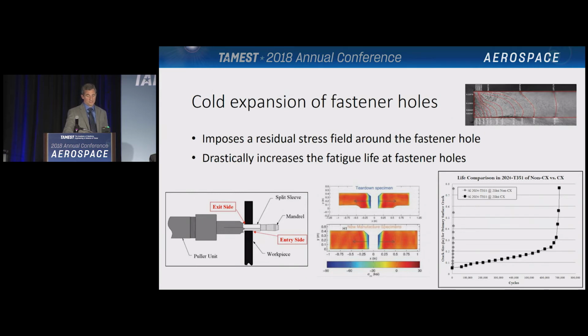So the picture on the bottom left shows how this is performed. A mandrel with a sleeve is put into a fastener hole, and then the mandrel is pulled back through the hole with the sleeve kept in place. Because the end of the mandrel, shown here, is bulbed, it pushes the sleeve into the material around the hole, stretching it to a larger diameter. This stretching causes the material at the hole to have a large compressive residual stress, which is shown in blue in this center plot here. The large compressive stress squeezes flaws in the material, making it more difficult for them to grow as fatigue cracks.